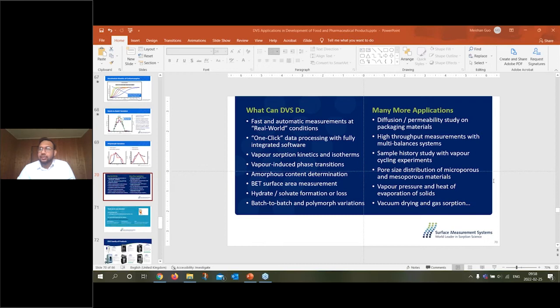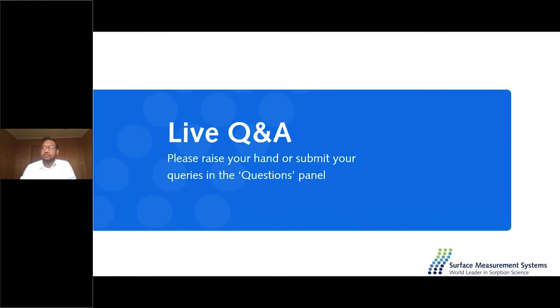Okay. The next question is, how does BET surface area compare with liquid nitrogen measurements? So basically, the conditions of the experiment are quite different. We are using the same equations, but we are using different probe molecule and different conditions for the experiment. The nitrogen sorption will perform at liquid nitrogen low temperature, and also vacuum for the degassing, which probably will destroy some of the structure inside pharmaceutical material, and maybe also losing the hydrated state of the material. So the surface area you measure with nitrogen should not be very representative when using the real application. And in case of the DVS method, we will perform at ambient pressure and temperature using organic vapor, so the measured value is more close to our real value we use in our applications. But if the sample is stable at different temperature, the result should be comparable as well.